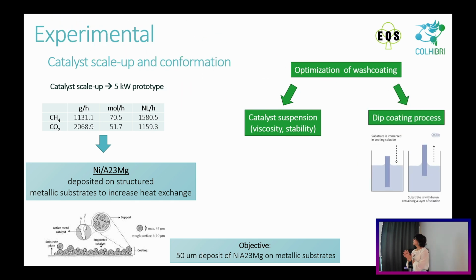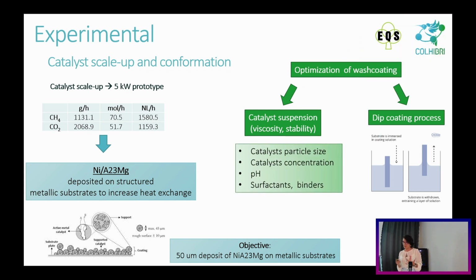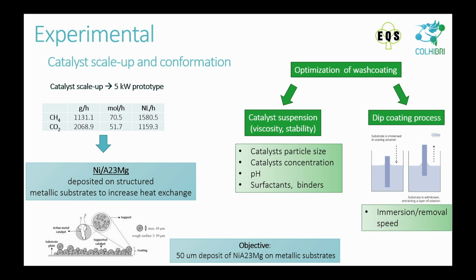So basically, the wash coating process involves the immersion of the structure in the catalyst suspension, which needs to have the right viscosity and stability. So when we remove it from the suspension, the catalyst stays on the surface of the structure. The parameters that we had to optimize are the catalyst particle size, the catalyst concentration, the pH, and also the percentage of surfactants and binders. And regarding the dip coating process, we had to study the immersion and removal speed.